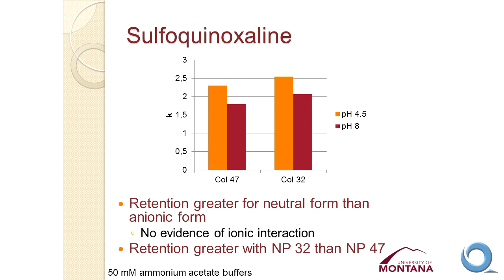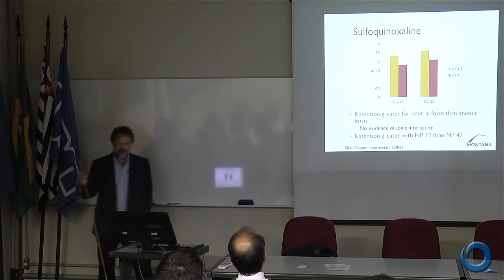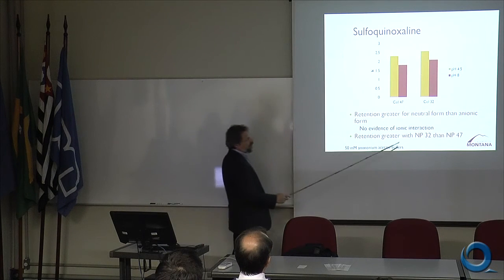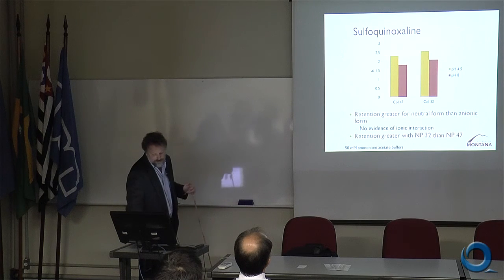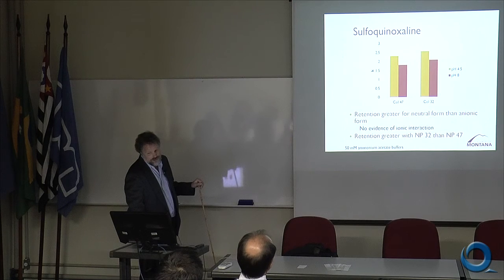We could look to see whether ionization of this molecule would, in fact, cause higher retention. And so we looked on both of our columns, column 47 and column 32, at low pH where it's neutral and at high pH where it's anionic, and in fact we see less retention of the anion. So apparently there's no strong ionic interaction with the nanoparticle which will cause higher retention of anions on the surface. If you think about that electron microscopy slide, it could be that we're still not getting a fully uniform coating of these silica surfaces, and so we actually have a silica surface which is in part anionic and is not going to be very attractive to the anionic molecules. It's just really hard to know at this point exactly what's going on, but for sure these particular surfaces are not retaining anions.